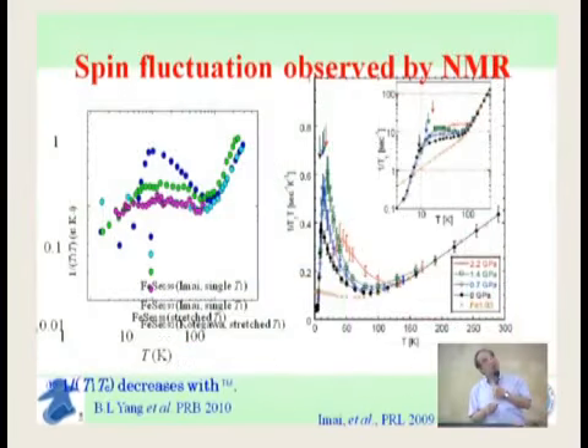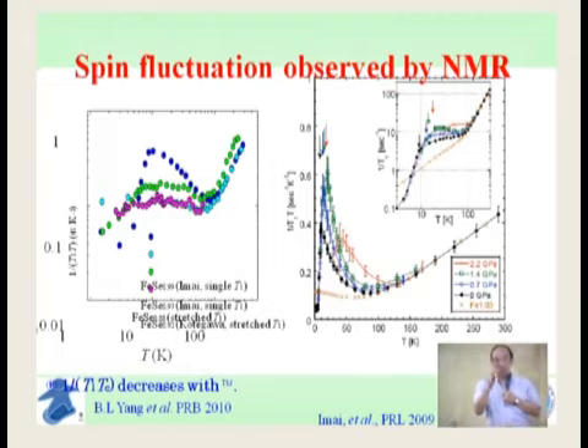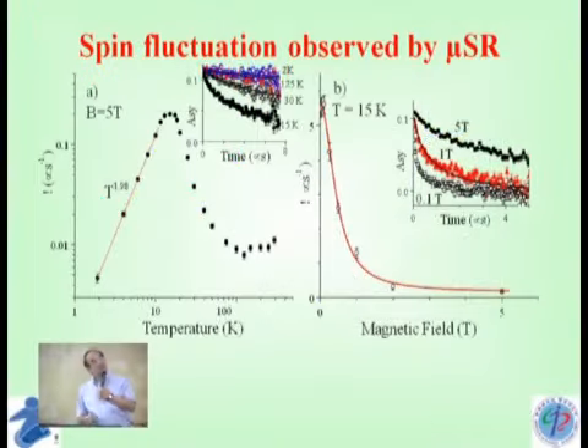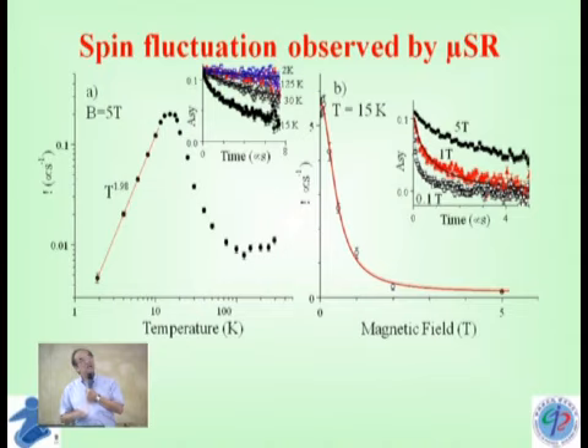Okay? And we can use NMR to look at some of the fundamental features by looking at the dynamics of the electron, and it shows that there is a so-called spin fluctuation. These are two different works. This one is from our group. This one is from a Canadian group working together with a Princeton group in the United States. They also show that around that temperature, the signal from NMR goes up. It's like this, and that indicates the spin, which used to be ordered, now becomes disordered or fluctuating because of this change. So there is no more spin order. And I collaborated with somebody in Canada using the so-called muon spin rotation. They also support that there is a spin fluctuation showing up at 100 Kelvin.